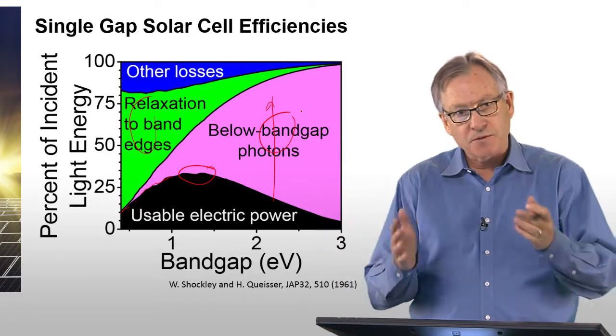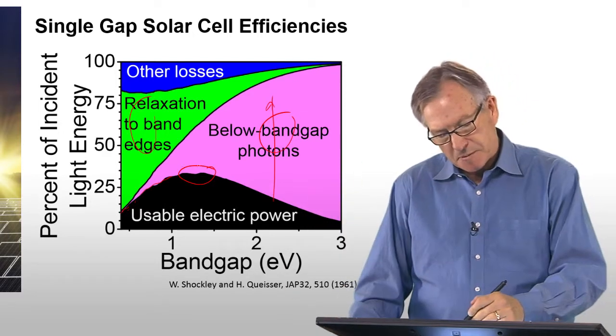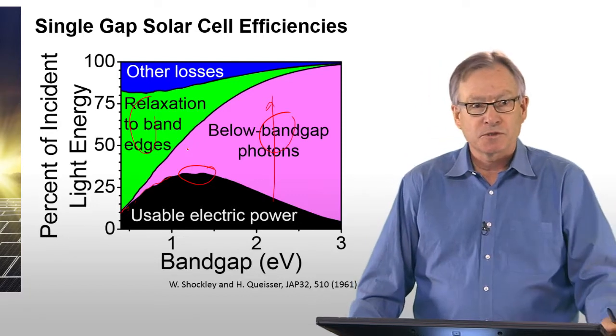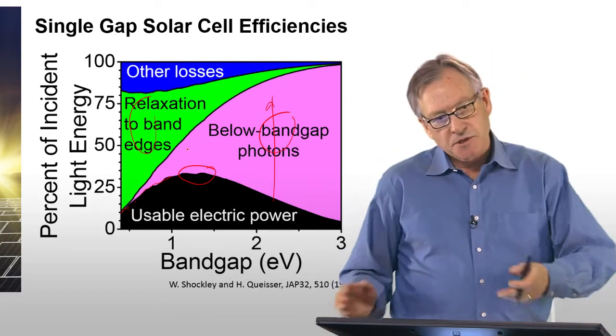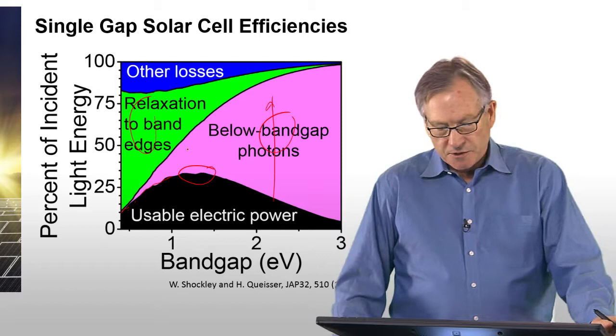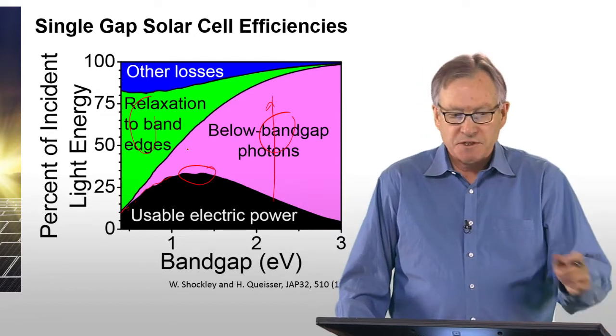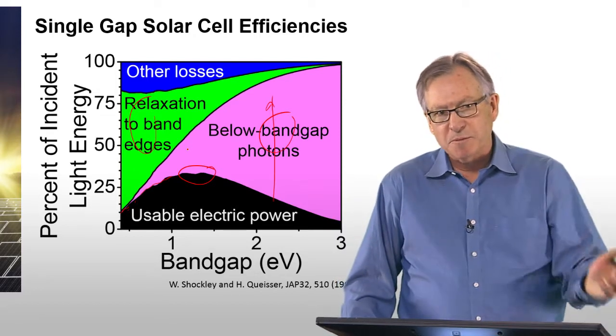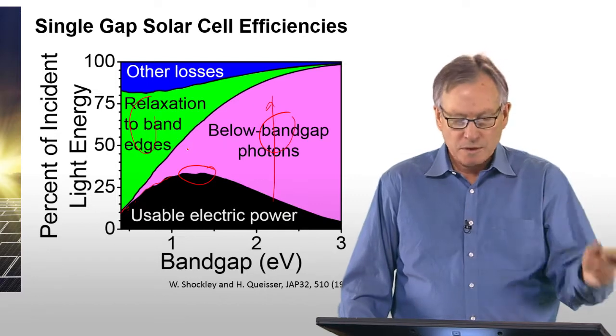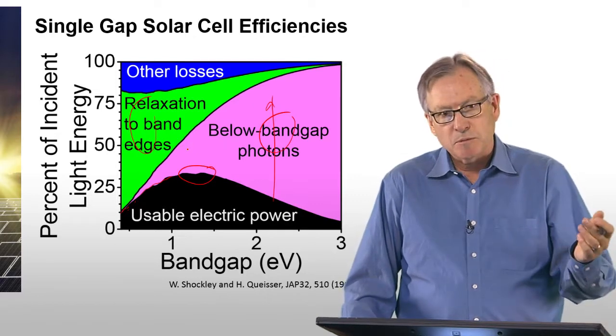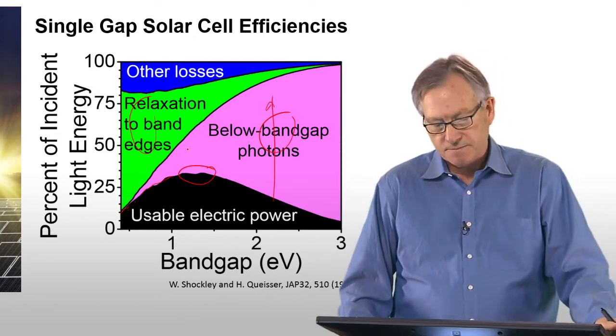So in this trade-off, there's an optimum, and the optimum actually fortuitously occurs around the band gap of silicon and gallium arsenide. And so in this range, it turns out that silicon not only is an earth-abundant material, but it turns out to be very favorable for reaching the maximum, what we call Shockley-Queisser efficiency.